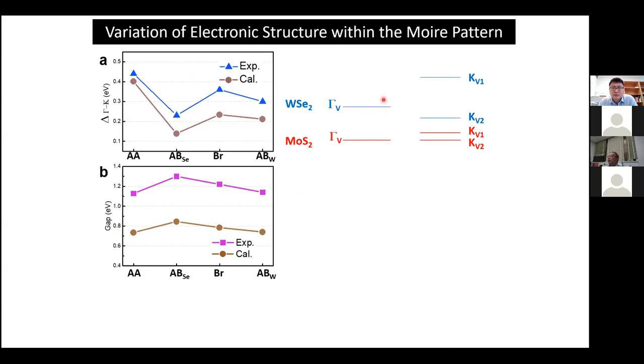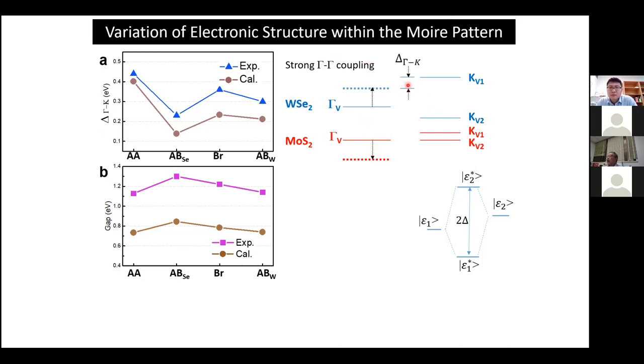Let's just think about before they couple, this will be the valence band location in the gamma and the valence band location in the K. Now when the two couple, let's first ignore the KK coupling because that's a lot smaller. Let's just look at the gamma-gamma coupling. If the coupling strength is larger, then you will push this one up and push this one down more. So if the coupling is stronger, you're going to result in a smaller energy separation between gamma and K. If coupling is smaller, you're going to have a larger one.